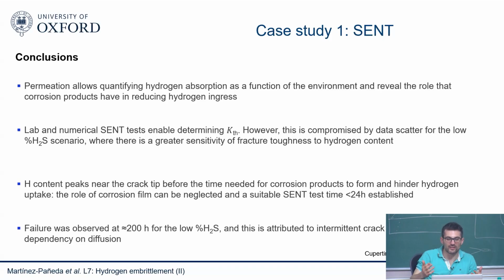And when finally we can explain the scatter in the experimental data based on the fact that we are in this regime where toughness is going to be very sensitive to hydrogen concentration, so therefore small changes due to these different corrosion products, different experiments will bring to those changes. But in the case that we have 200 hours, we're a bit puzzled with the experiment that failed at 200 hours. What happened in that experiment?